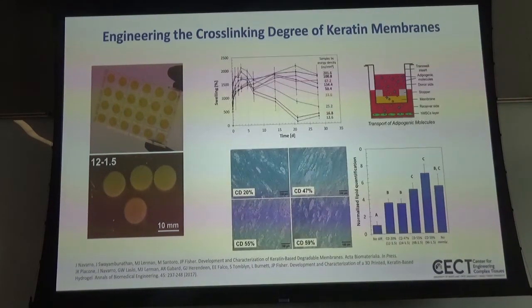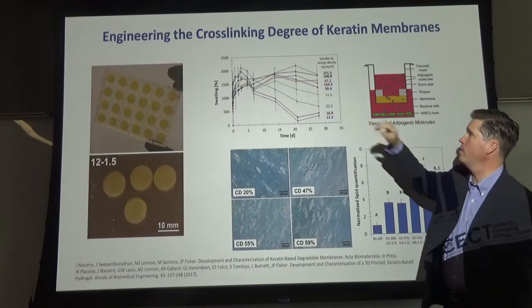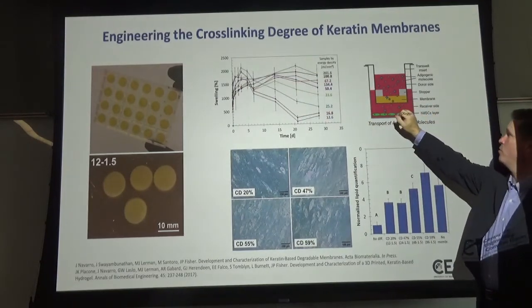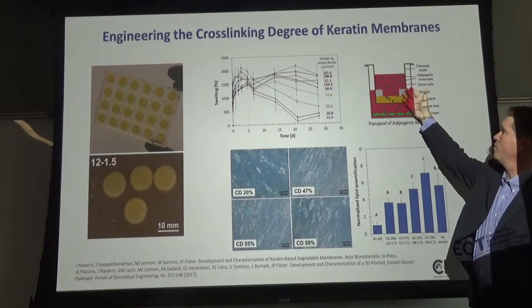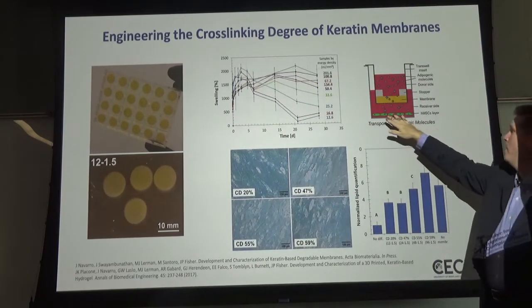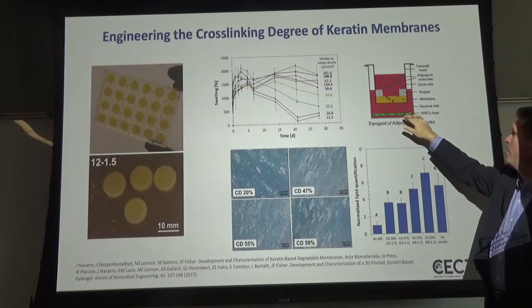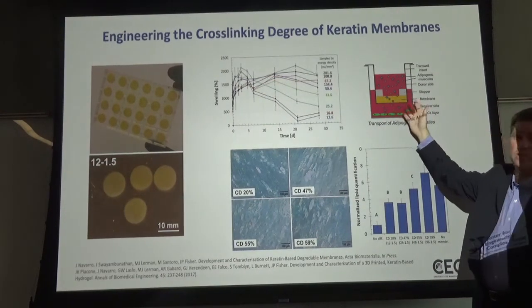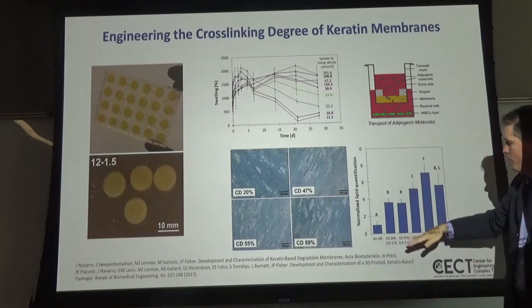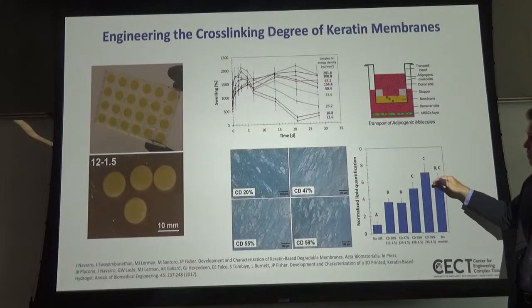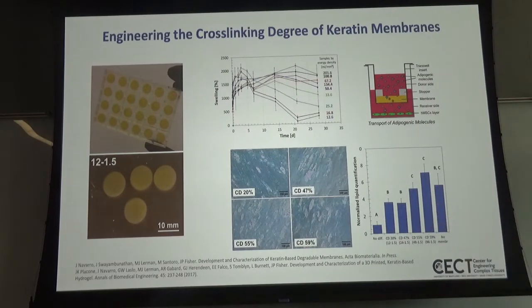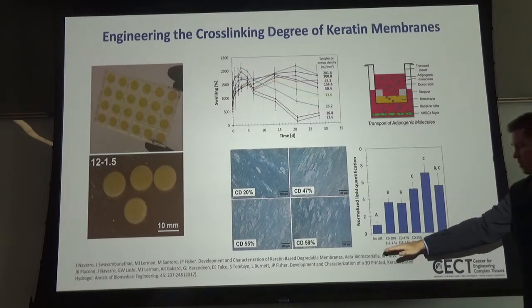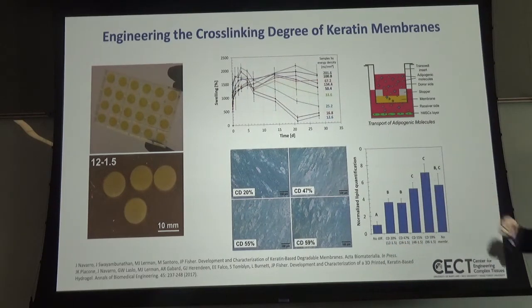Using this approach, Javier then validated that we could use the membrane to control molecular communication through the membrane and ultimately to a cell population. So first he characterized the swelling of the membrane, but then took the membrane, put it into a transwell, added adipogenic molecules to the top of the transwell, and then human mesenchymal stem cells at the bottom, and using different membrane types and ultimately different porosities or cross-linkings, was able to show that we can get different amounts of lipid expression as a marker of adipogenic differentiation by controlling the membrane type that was used in the transwell.